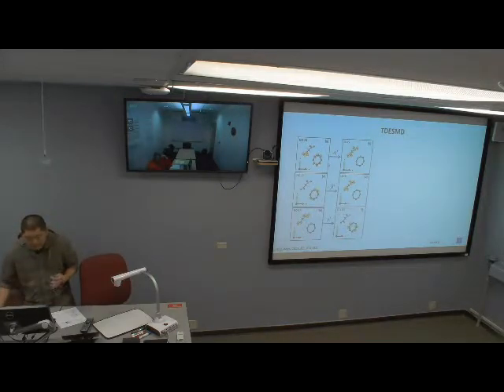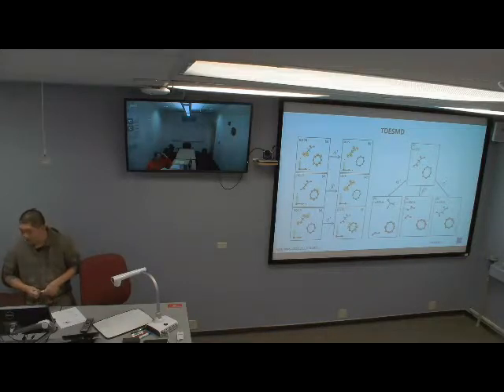As we can see, for the first two transitions, the transition has charge transfer character from carbon nanotube to the molecule. But for the third transition, it has charge transfer character from the molecule to the carbon nanotube. And then we use these transitions as initial conditions for TDESMD calculations. And here is our result.